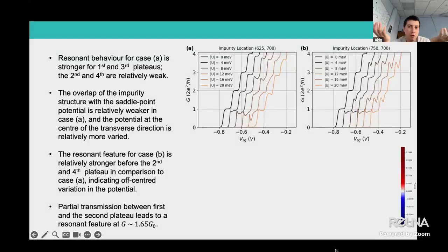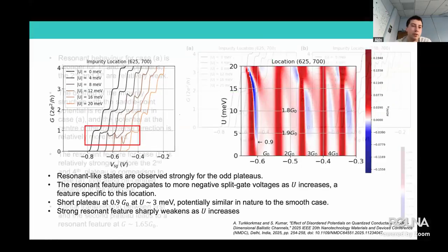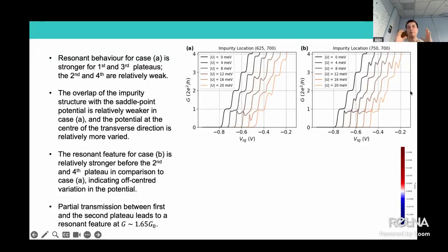Okay. So here there's an issue with my presentation. I'll talk about the effects that we observe from the conductance data. So as we move the disorder inside the structure, the superposition of the disorder with the confinement will change the nature of the effect. So instead of seeing stronger resonances in the middle, we will start seeing stronger resonances for higher plateaus. And this is because the density profile of different modes are different. So in the first mode, you have most of the density centered in the region, but the second eigenvalue it's spread. So as the hill and well-like impurities and disorder can interfere with the electrostatic environment, and that can create different behavior for different plateaus in the system.